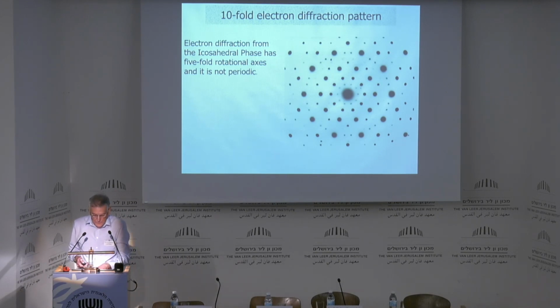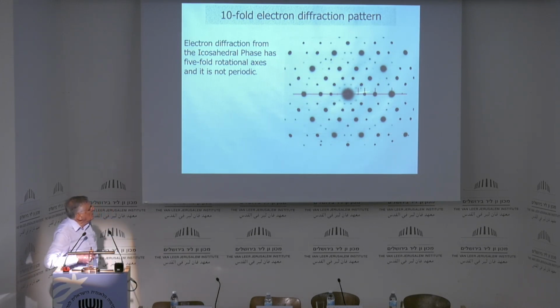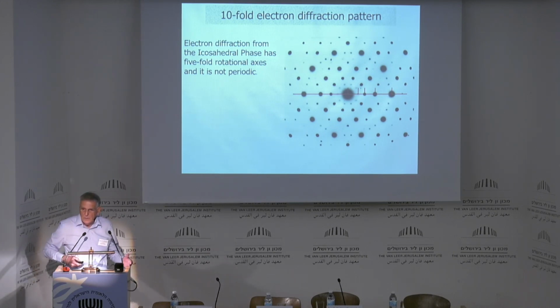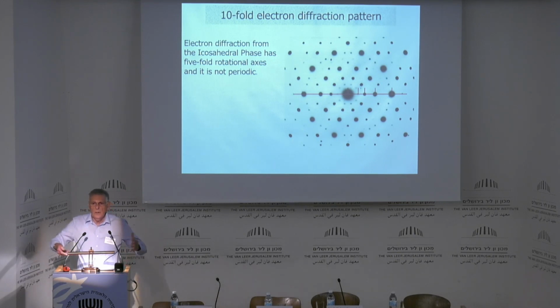But this diffraction pattern doesn't only have a strange rotational symmetry, it has no periodicity. So if you look at this red line that I just marked here, you see that if you take the distance, let's say from here to here, and you multiply by 2, you get there. And there is nothing there. No periodicity, 10 or 5-fold rotational symmetry. What's going on? So I will explain to you what goes on in my mind. I say to myself, based on past experience, this must be a twinned structure with very small twins. I will show you examples and explain exactly what I mean by that.